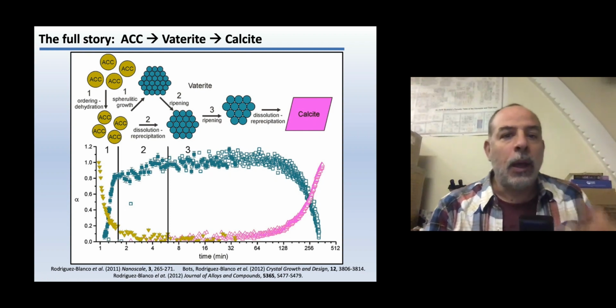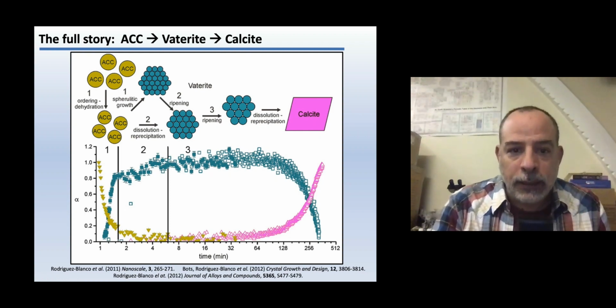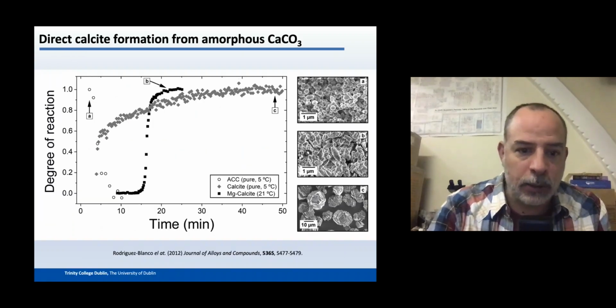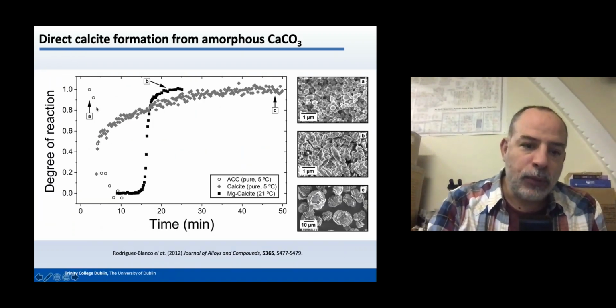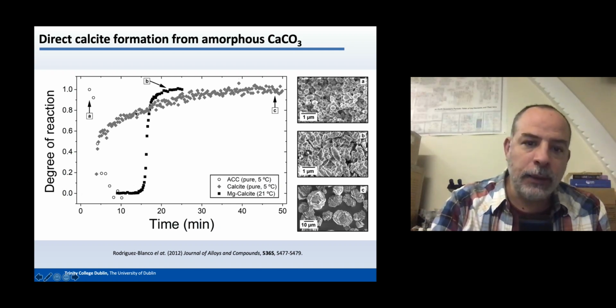All right, and we have done the same, for example, for the crystallization of calcite from amorphous calcium carbonate. This is what you can see here. This is, for example, the decay of amorphous calcium carbonate and the crystallization of calcite, these gray rhombs here, and also the crystallization of magnesium calcite.